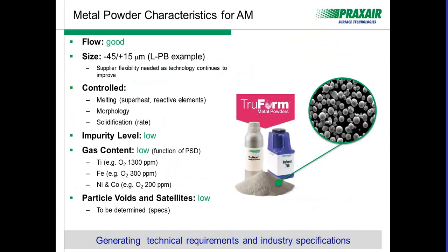When we look at particle voids and satellites, as I spoke about, that surface defect concentration can affect flow. And so how do you control that? We do specialize in making sure we create the optimum gas structure to not only prevent satellites, but to also prevent particle voids. And that has a lot to do with how the liquid is interacting with the gas. And we're going to show some examples of that using high-speed videos, as well as some schematics to talk through the interaction of liquid with high-pressure gas.